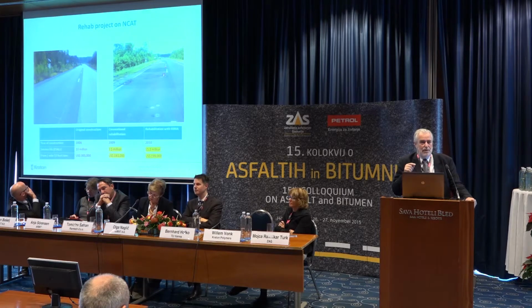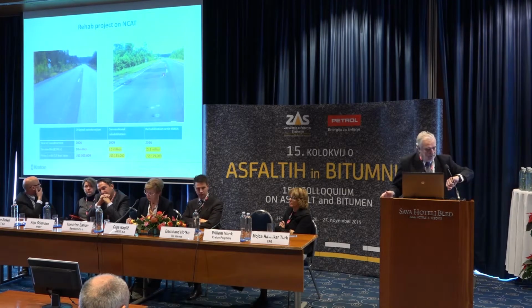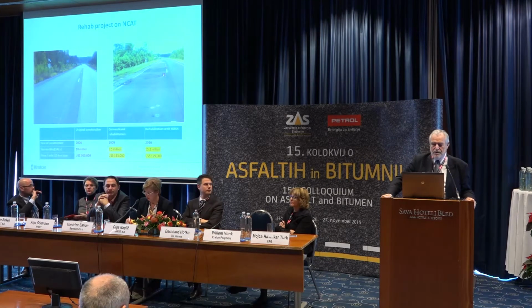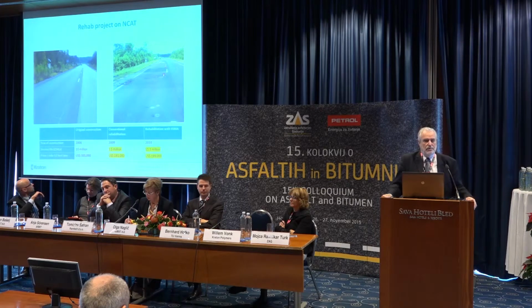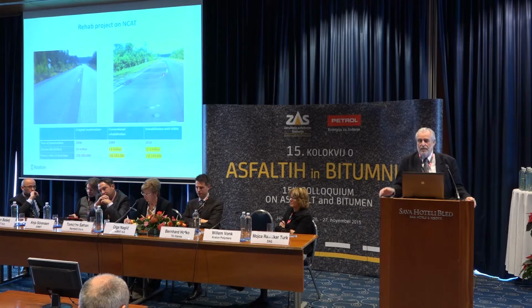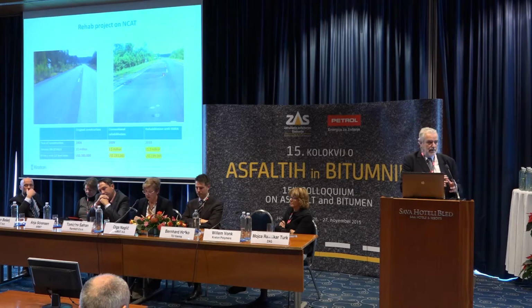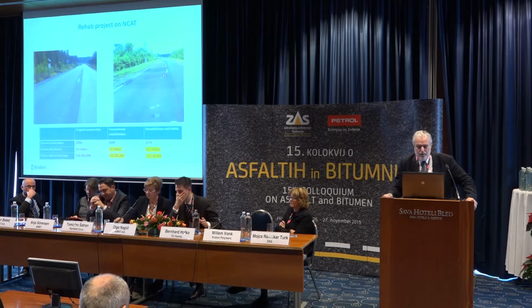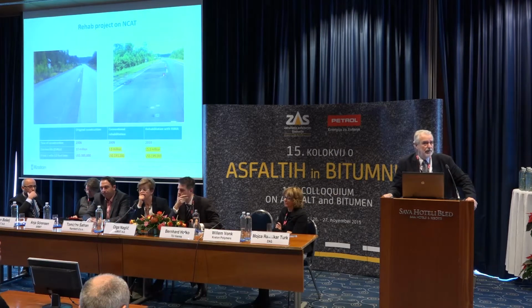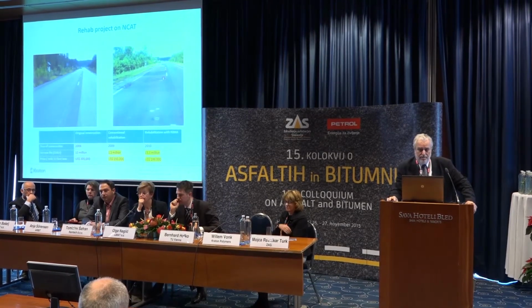There is even a more interesting, from my perspective, example of the potential of this material, because next to our section there was also a section from the DOT of Oklahoma, and they have been working with a section that was deliberately built on soft soil, and that had to be repaired after 10 million standard axle loads. There was a conventional rehabilitation which only lasted for 3.5 million standard axle loads, and that is the picture on the right-hand side. And then it was decided to rehabilitate this with a HiMA binder layer and wearing course. And on the left-hand side, you see what the status of this material is after 15 million standard axle loads, that is after the repair that has taken place.